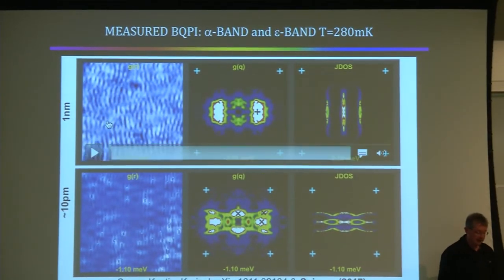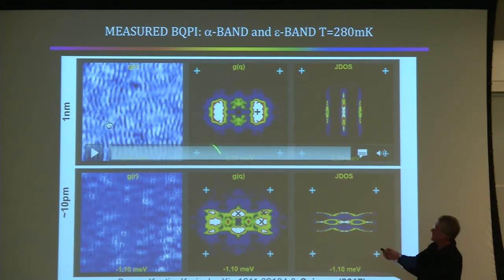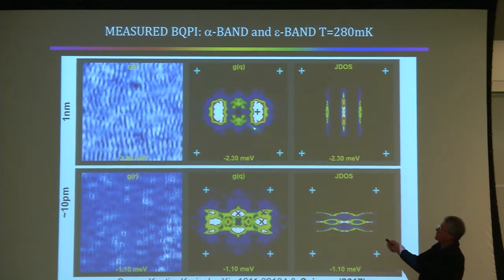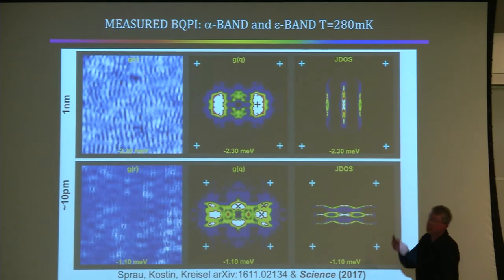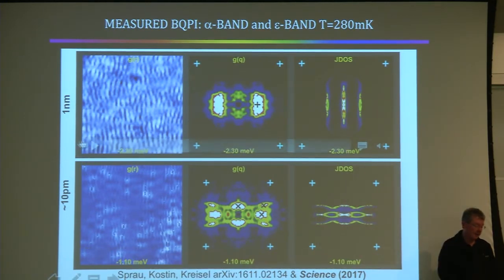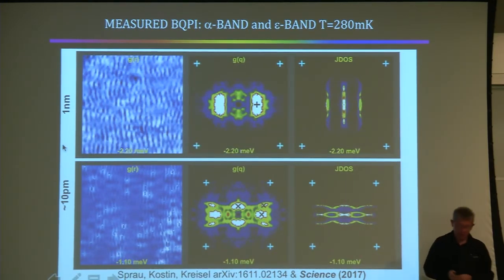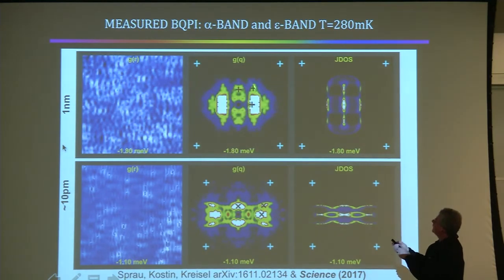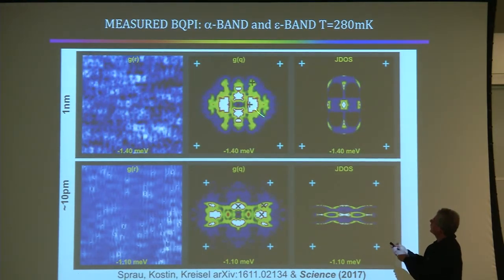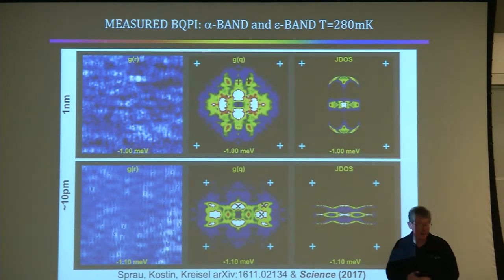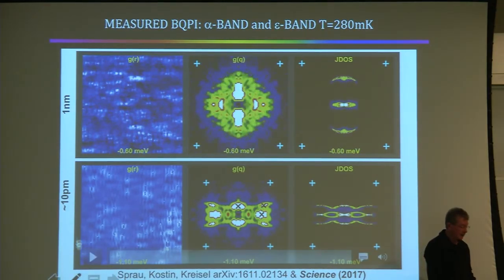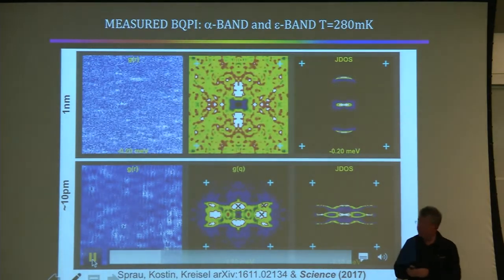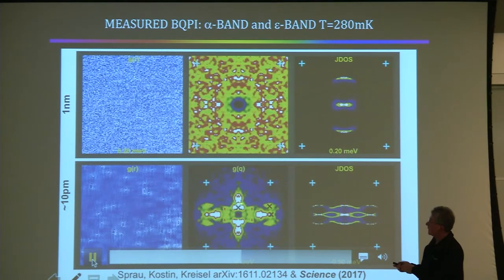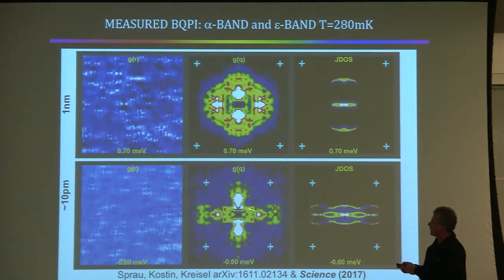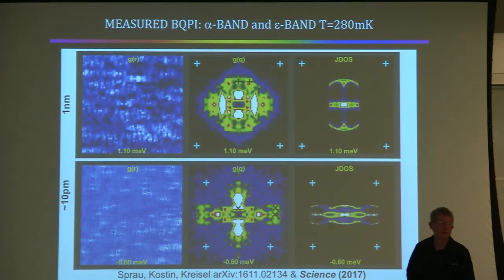We can visualize. This is an image of scattering interference of the quasi-particles. This is its Fourier transform. This is a model for what should happen on the band in the center of the zone. And indeed, we see the 3 Q vectors we're looking for, and they're moving to the locations that we expect. And then similarly, we can do the same thing for the other band near the pi0 point in the zone, and also follow those 3 Q vectors.